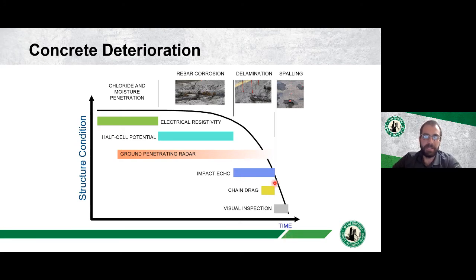The typical methods that we use, hammer sounding, chain drag, and visual inspection, these really identify late stage deterioration, right? Chain drag and hammer sounding can only find delaminations when they've become large and near surface, so they're late in the delamination phase. Visual inspection, when we start to see spalls and surface cracking, is pretty late in the damage stage. But there are other parts of that phase. We start with chloride and moisture penetration. We then move on to corrosion of the rebar. That rebar starts to grow, causes cracking, and then delamination, and then spalling.